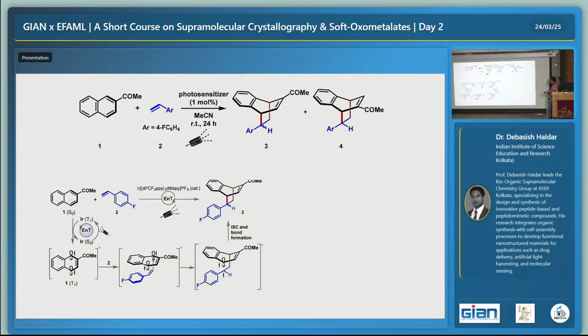So with the photosensitizer, in methyl cyanide, acetonitrile, room temperature, 24 hours with a blue LED, this reaction is happening. This naphthalene derivative is reacting with this, going for a Diels-Alder reaction. From a two-dimensional structure, it is forming a three-dimensional structure. And what Biplav mentioned in his paper is that this is actually about the stability of the transition state. So if you can make the transition state stable, then the reaction can happen. And how to make the transition state stable?